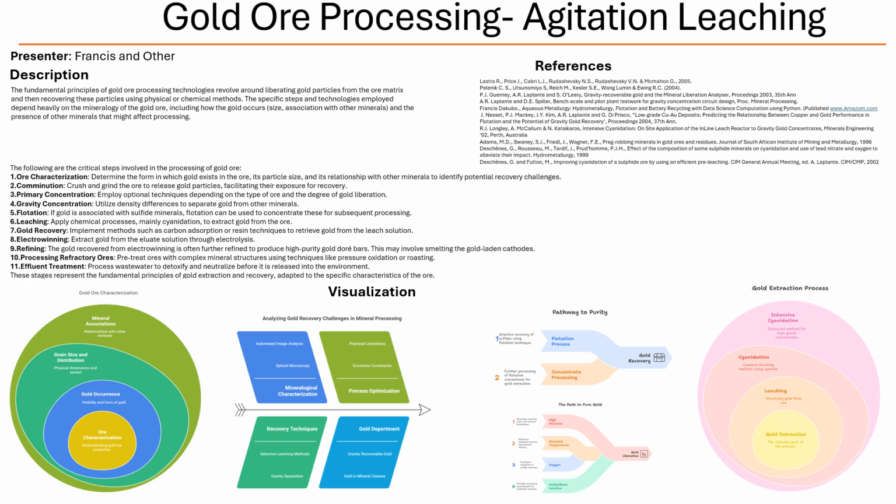And CIC? CIC is a bit different. In CIC, the pregnant solution, the solution containing the dissolved gold, is passed through a column filled with activated carbon. So the carbon is kind of like a filter trapping the gold as the solution flows through. Exactly. And each of those processes has its own advantages and disadvantages. Like what? Well, for example, CIP is generally more efficient in terms of gold recovery, but it requires a more complete leaching of the gold upstream.